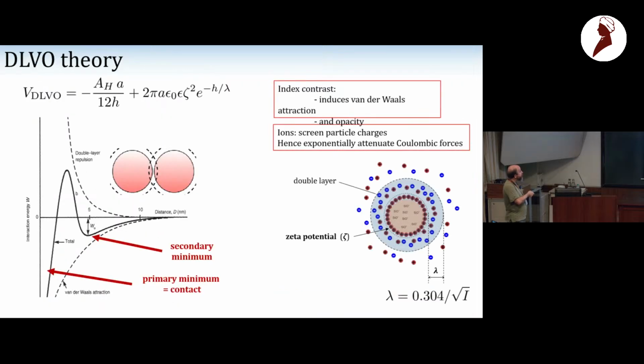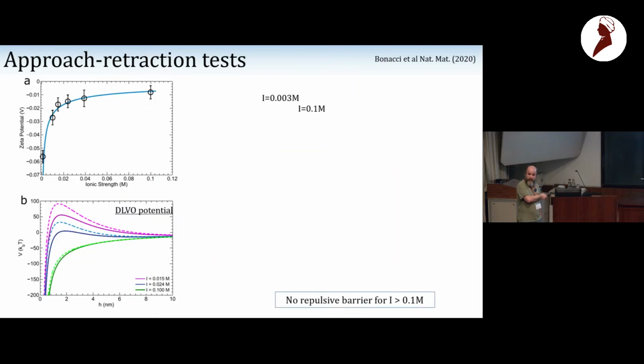The general idea is that when you have the DLVO potential, you have a primary minimum where particles are in contact, you have a secondary minimum, and normally if you want a so-called stabilized suspension, you try to have this barrier and to play here. But the point is that when you have ions and significant index contrast, basically this barrier will totally disappear. And in that case, you are in a system which is essentially adhesive.